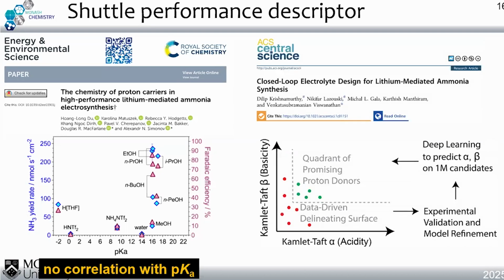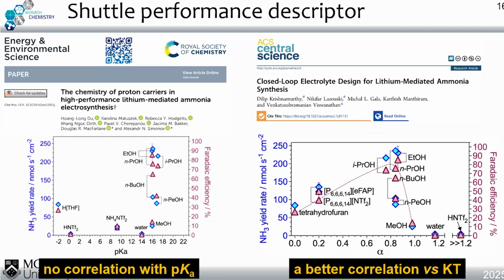Therefore, we looked to our MIT colleagues, and they proposed a more complex approach, which is solvatochromic parameters, where alpha stands for acidity and beta stands for basicity. We applied this to our research, and now we could see a better correlation. When you increase the acidity from 0 to 0.8, you can see an increase in performance. As soon as you go beyond that, it degrades significantly.